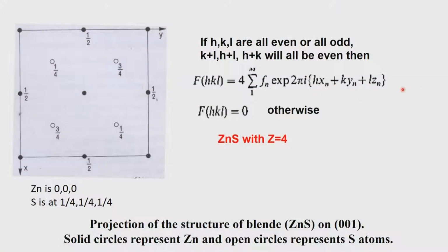What is very important now is that we are directly getting the expression for the structure factor, which can undergo a Fourier transform to give the electron density. What we are not worried about at this moment, which we should worry about, is how to determine the phase. We have the value of fn, we have the values of h, k and l, we do not have xn, yn, zn. In this example we are taking, we have xn, yn, zn. So, we can get the expression for I of hkl, and from that we can get the expression for F of hkl.